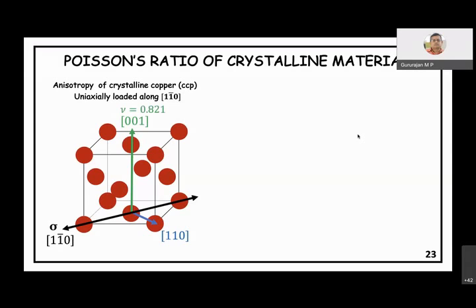So the two values are very, very different, different in magnitude, different in sign. So are there surprises here? Most students who have not heard of negative Poisson ratio will first express their surprise at the negative value, that how can Poisson ratio be negative. Negative Poisson ratio means that if I am stretching a rod, then in the transverse direction also it is expanding instead of contracting. So that seems to be quite counterintuitive. So negative Poisson ratio can be one surprise.